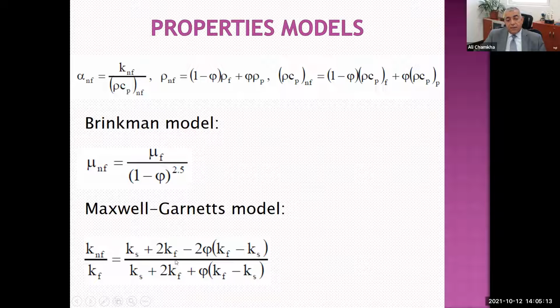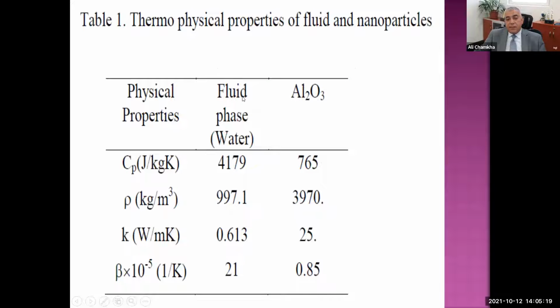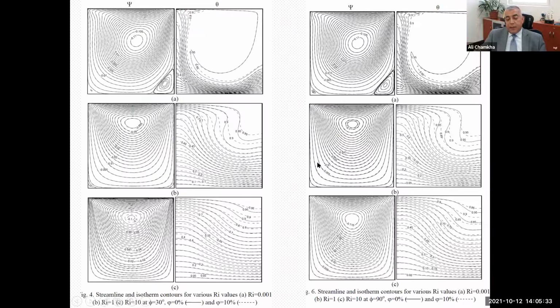For the thermal conductivity model, we use the Maxwell-Garnett model. This is the model. And then we predicted these are some properties for the base fluid, being water here, and alumina. You will see the thermal conductivity is 0.613 for the base fluid water, while it's 25 for the alumina. Mixing those together will give you a better performance in terms of heat transfer.